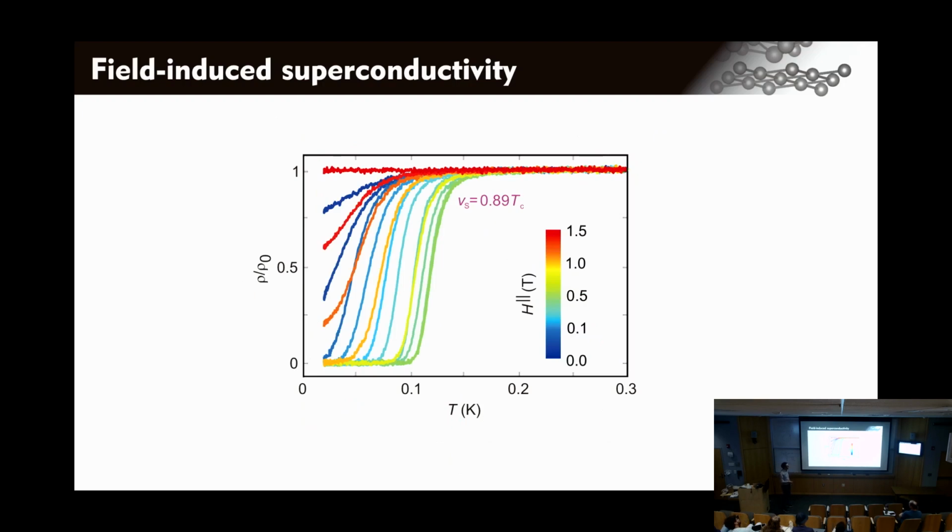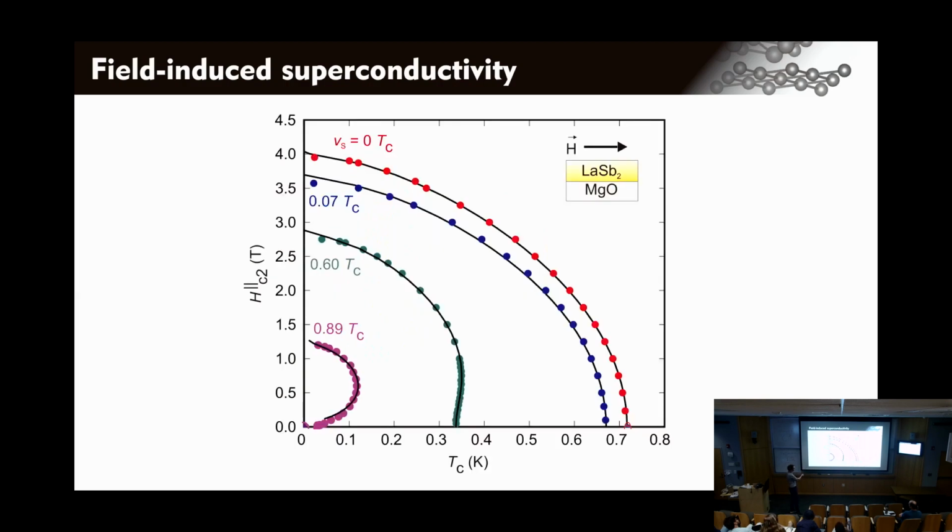It's kind of challenging to measure because the temperatures are very low. And small angular offsets are very difficult to compensate, but we can manage that. So the blue is a zero field, and then getting towards green is about half a Tesla, where we have this nice zero resistance state, and then going to higher fields, red, it disappears again. So this is just characterizing this dome.